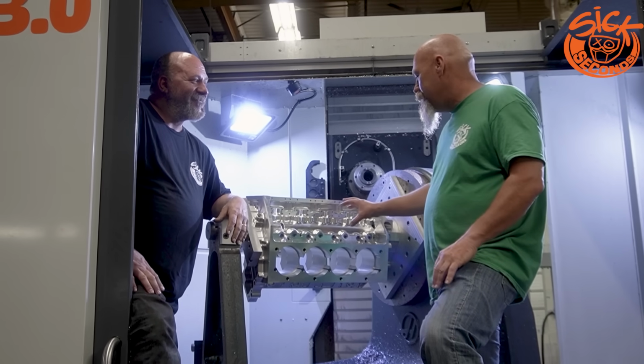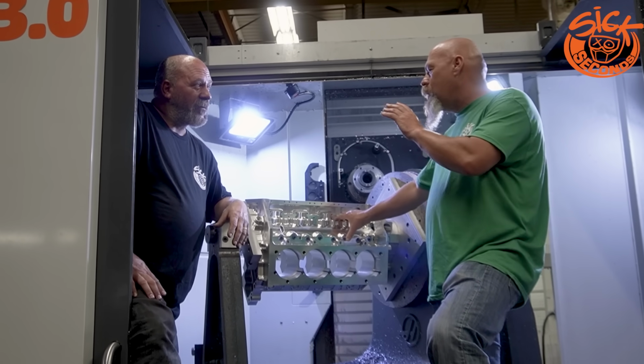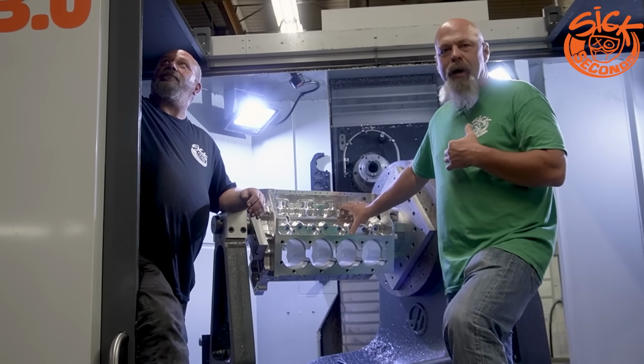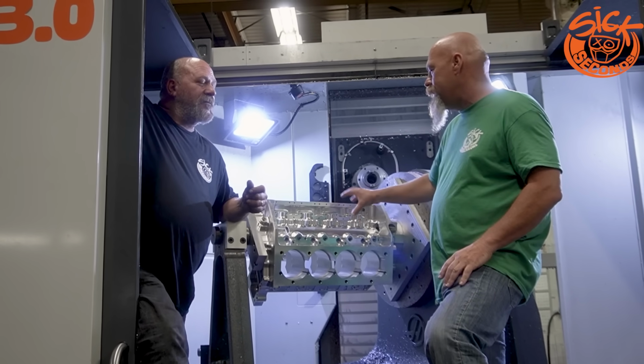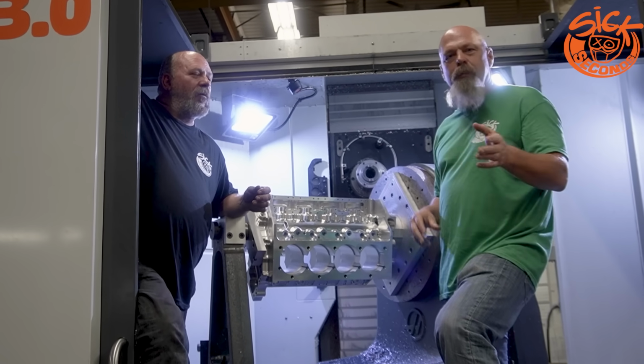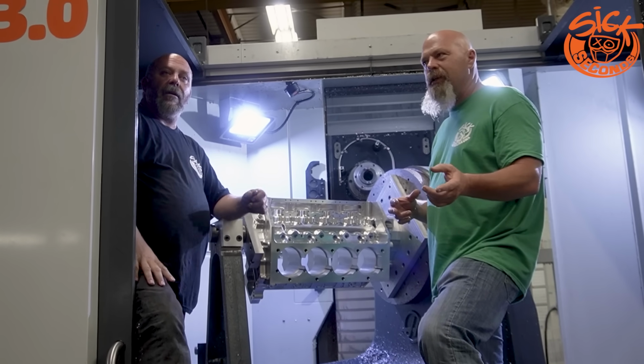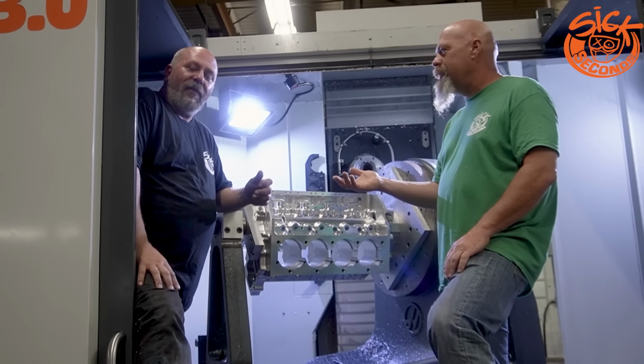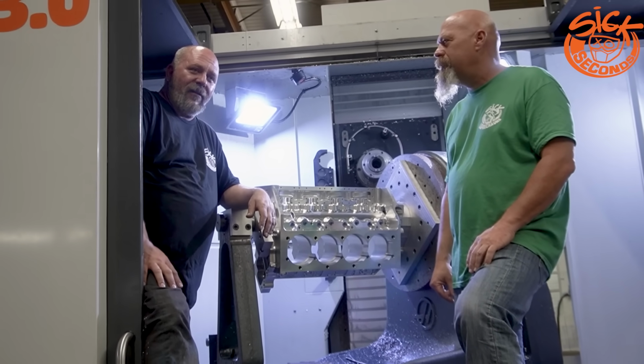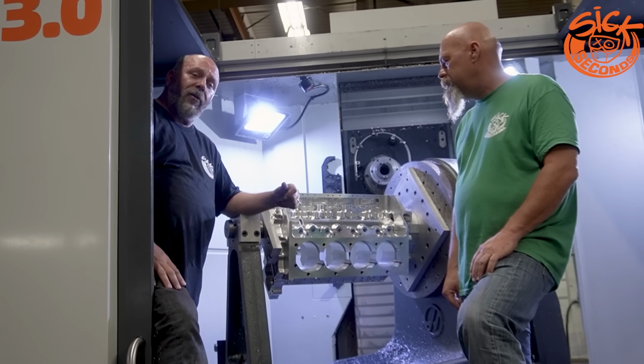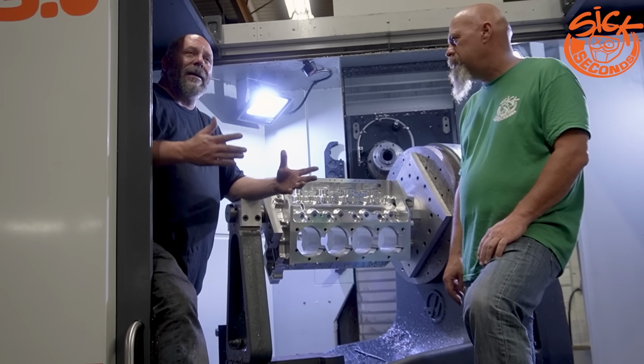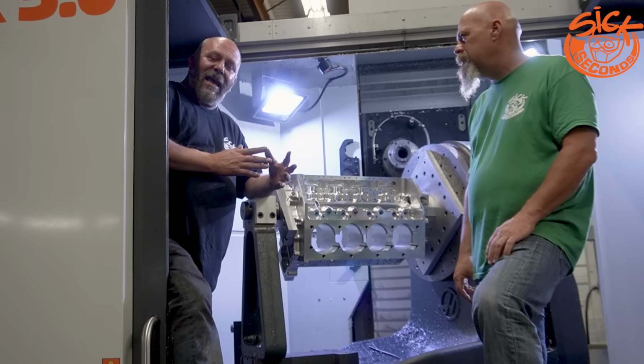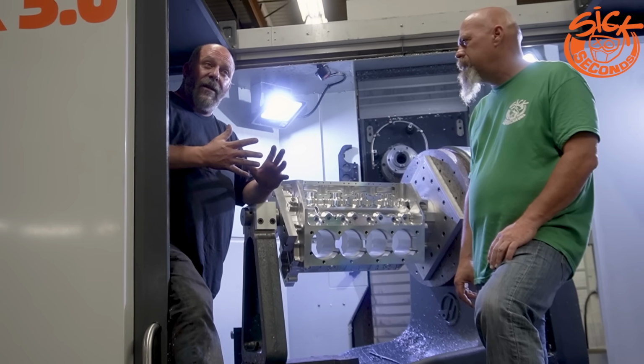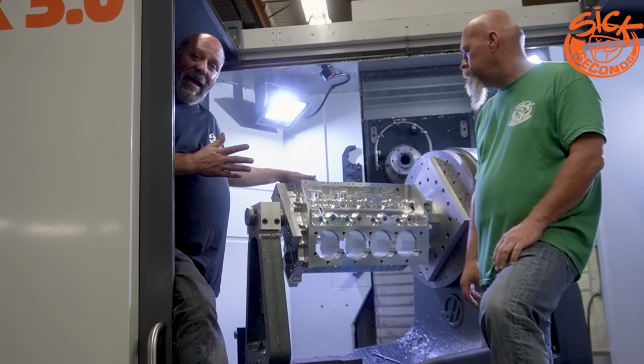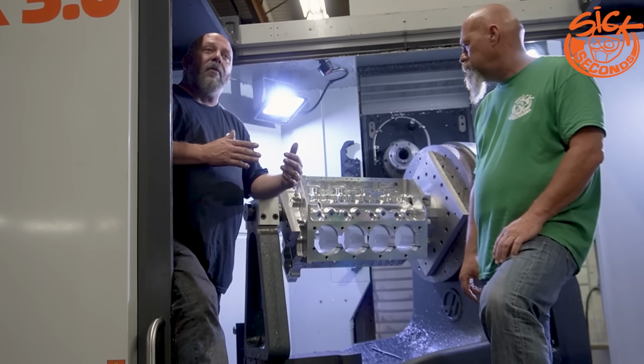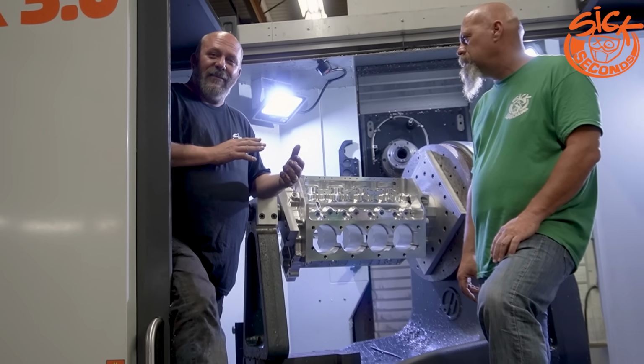Block number 1 was the one that was started and heat treated while it was still at my shop. And then block number 2 was the first one they cut and said, okay, with the 4 inches, this is how much material we should take off, and then the heat treat would do that. Well, when it got back from heat treat, we started to machine it. We put the cam bore all the way through, like what we had done, and then we realized that as we were doing other machining and started doing a ton of removal on the bottom side, the bores started going out of round.